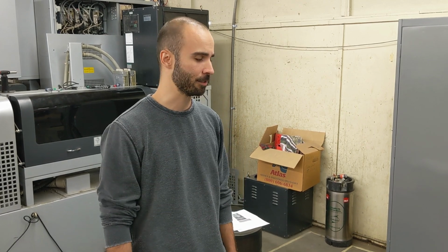So why do we need a bender? Well, it turns out that welding steel, specifically AR-500, is a really, really bad idea because you locally temper the corners of where you welded, and that creates weak points. And so you can imagine if you get hit really, really hard on that weld, it's probably going to break. We really want to have nice, strong bends instead. And so this is why we built the bender.